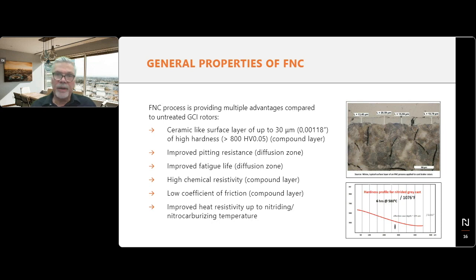So this is basically a summary of the suit, why basically FNC is suitable for the application. What is interesting here is that on the right-hand side, you can see probably the metallography, and the metallography really shows a cast iron, a gray cast iron, which has been nitrided. So very difficult to make out the white layer on top, but it's there. On top, there isn't much different background. It's sort of grayish, but this is just the way the sample has been mounted. And inside the structure, what you can make out, those gray flakes are basically graphite flakes.